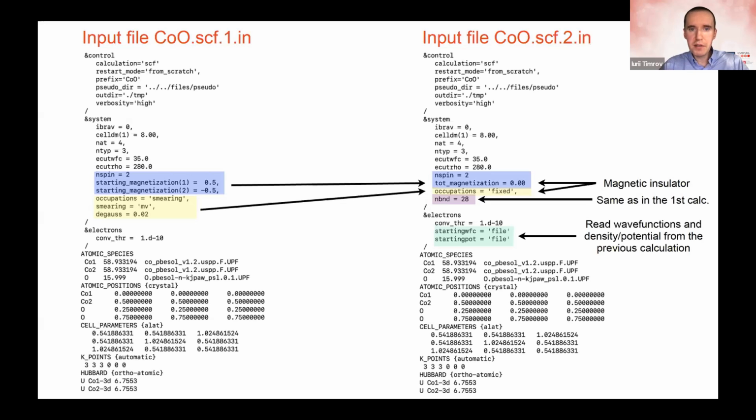In the first calculation, which was the DFT calculation, that was the metallic ground state. You remember we computed in exercise 1 the projected density of states, and we saw that it is metallic. But now we apply plus U, and we remember from exercise 1 that when we apply plus U, it opens a gap. So we went from the magnetic metal to magnetic insulator.